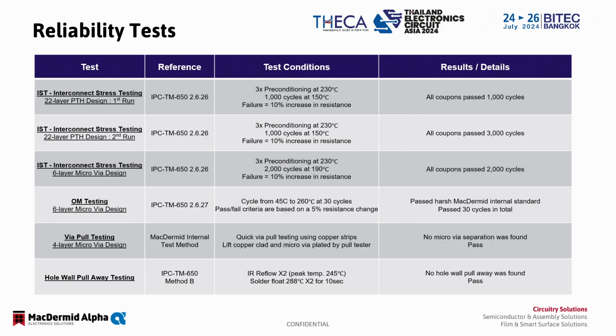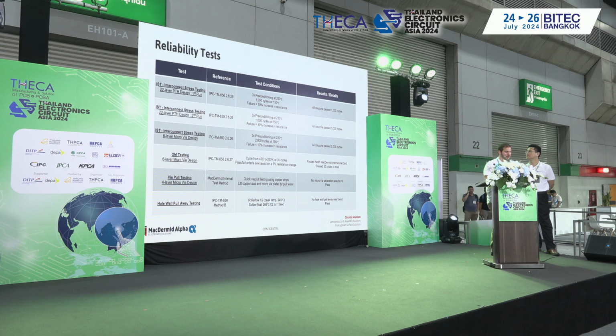To add on to that, we did another series of reliability tests to make sure that there was no other common ones. I won't go into as much depth in these, but we did the IST22 layer. We did a 6-layer microvia design to check that the microvia reliability and capture pads were clean and good. We did OM testing. We did via pull testing to make sure that the weak point in our vias was not at the connection between the direct metal and the acid copper, but at either a joint of the inner layer or on the surface. And then we did a hole wall pull away test to verify that we weren't seeing a lot of recession in the through hole feature itself.